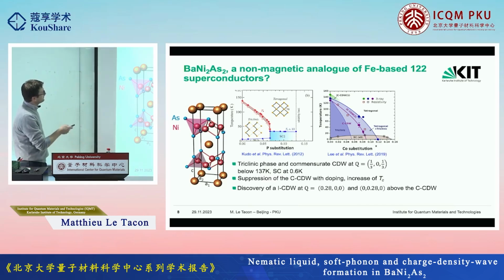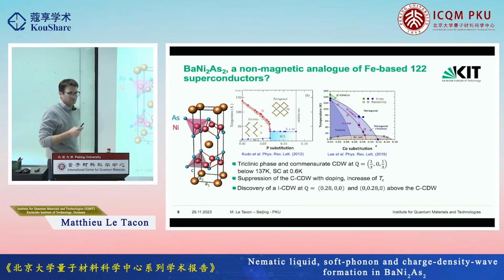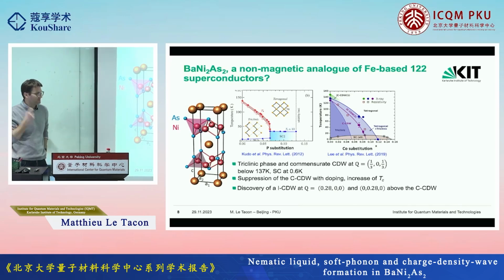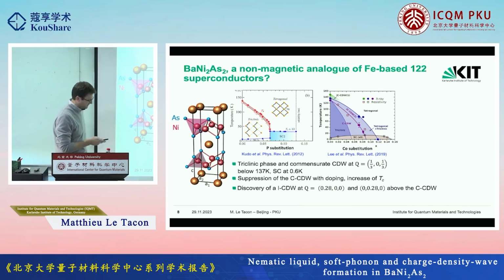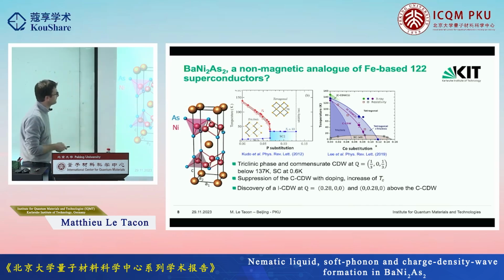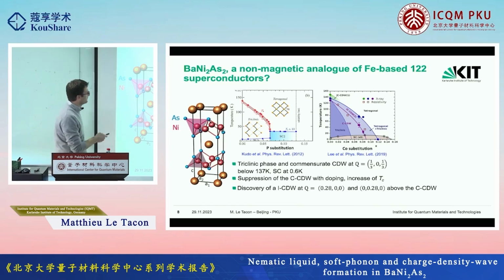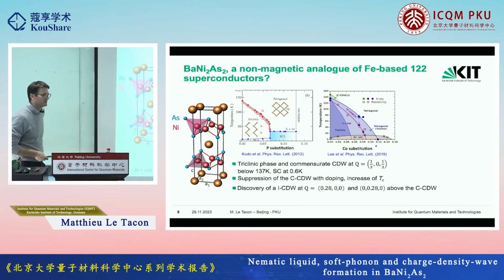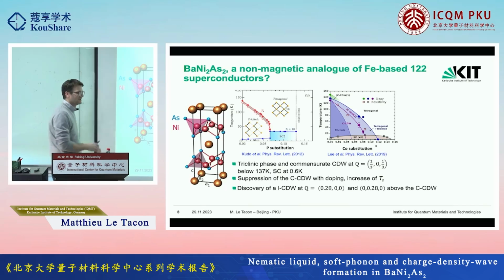And in this phase, what you have is basically a transition from the tetragonal system to a triclinic phase. And nobody who is a bit sensitive and likes to work in reciprocal space likes to work with triclinic crystals. I think the space group here is P1 bar. So you pretty much broke all possible symmetries.